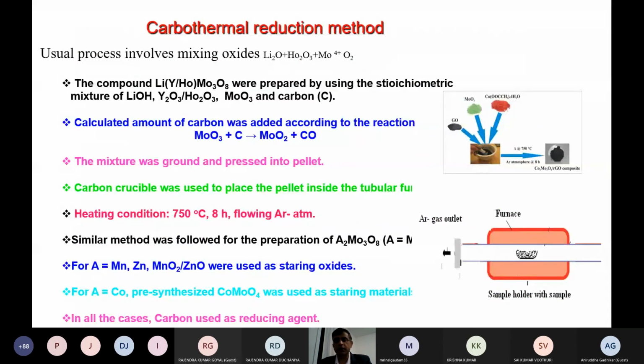So here, remember, we cannot use molten salt. Here we would use the carbothermal method, meaning carbon. Remember, here molybdenum is in the 4+ state. I told you, usually, if you want to prepare some material commercially, they use sealed tube reactions. They try to prepare MoO2, meaning reduced to 4+, and use some expensive technique: you seal the sample, put it at high temperature, and get the respective oxide. So what we do is the same, but we try to find a simpler way.